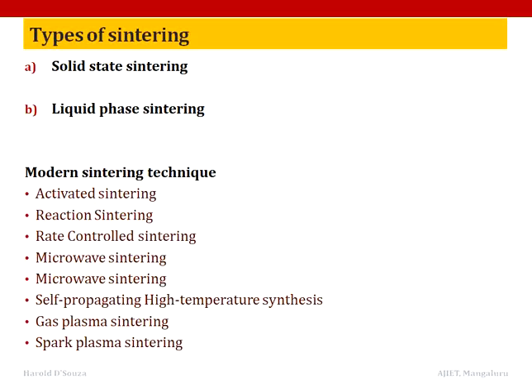Now, reactive sintering may involve a transient liquid phase. Reactive sintering is nearly spontaneous once the liquid forms, which provides the capillary force leading to the densification. Now, reactive sintering has been successfully used to process various aluminide type intermetallic compounds. Reaction sintering may also involve heating in a gas atmosphere which reacts with the powder compact, resulting in the formation of the desired compound. A typical example is the production of reaction bonded silicon nitride, made by sintering a green compact of silicon powders in nitrogen atmosphere at 1523 Kelvin to 1671 Kelvin.